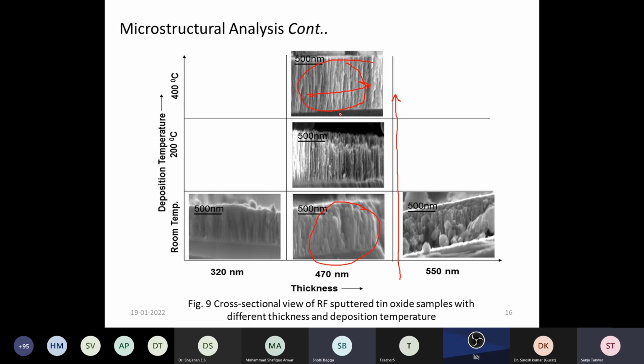But for the sensing application, our film should be highly porous. So that's why we have chosen this 470 nanometer film for deposition at the different substrate temperatures. But this is giving me only a qualitative analysis. To quantify it, we have to do some other experiment. For this, we have used the optical properties, because as all of you know, if the material is too dense, its refractive index will be higher, while if the material is less dense, its refractive index will be lower. So by measuring the refractive index, we can say how porous the film is, so we are able to correlate sensing with the optical properties.